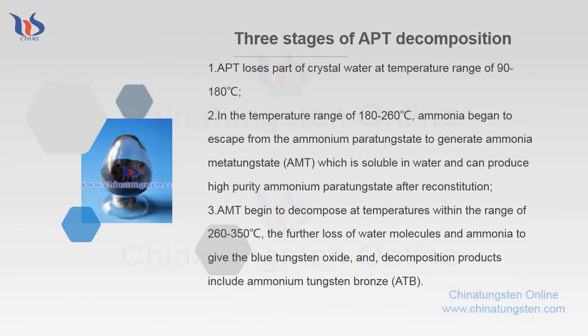Research on Ammonium Paratungstate decomposed to Blue Tungsten Oxide under a reducing atmosphere found that decomposition of APT has experienced three stages. Stage 1: APT loses parts of its crystal water at a temperature range of 90 to 180 degrees Celsius.